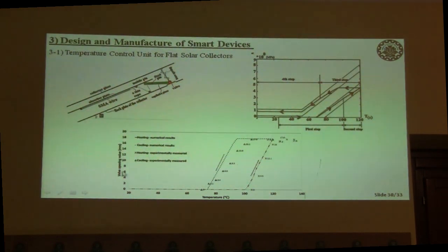You can see here the valve opening with temperature. The dashed lines are our numerical predictions, and these spots are experimental findings. For example, we were planning to completely open the valve at 120 degrees, and experiments showed that nearly at 140 degrees the valve is completely operated.